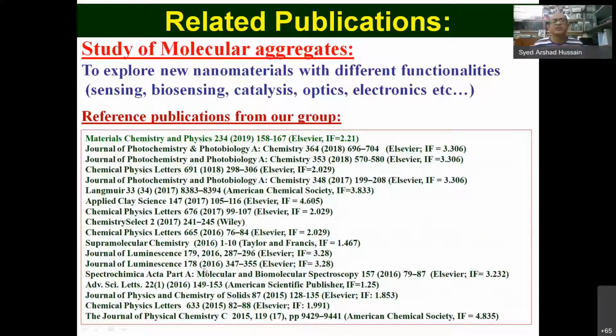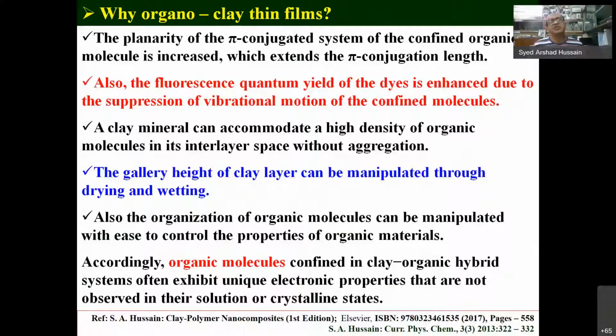These are some supramolecular systems using clay. Now, why is this clay organo system important? This is because the planarity of the pi conjugated system with the confined organic molecules is increased when it's incorporated in the systems, and as a whole it extends the pi conjugation length and hence the electronic behavior. And also the fluorescence quantum yield of the organic materials is enhanced. Why? Because when you incorporate the material in the clay systems, it suppresses the vibrational motion of the confined molecules. So quantum yield is enhanced, and again its electronic behavior changes.